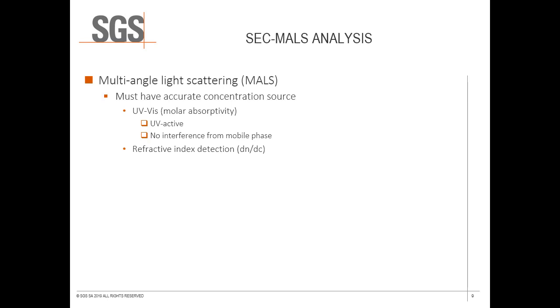The differential refractive index increment, DNDC, is the change in refractive index of the solution when the solute concentration is changed. Good DNDC values directly applicable to your sample are often difficult to find in the literature because DNDC values are specific to the sample material, mobile phase composition, temperature, detector laser wavelength, and even the molar mass of polymer samples if the molecular end groups affect the refraction of light differently than the repeat units.